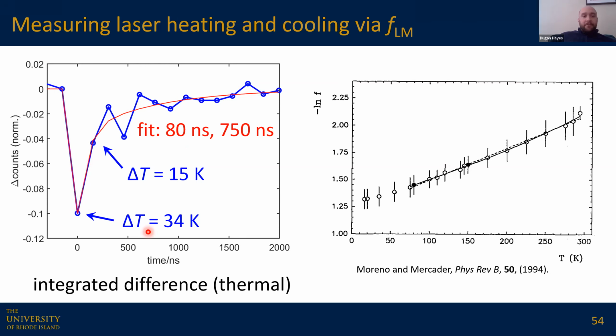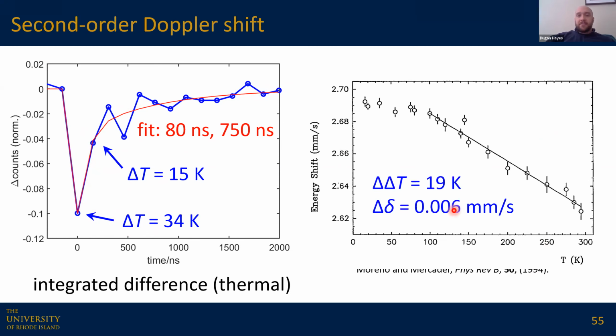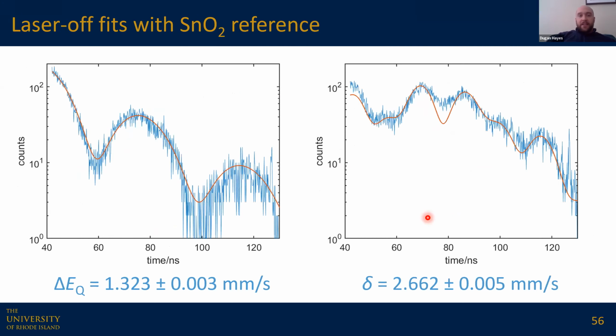And we can fit the recovery of that and see how much the temperature changed at two different time points from this data from 1994, where we can look at the Lamb-Mössbauer factor as a function of temperature. We can then correlate that to the second order Doppler shift for the same material and see that we get a very small change in isomer shift that we'd expect here.